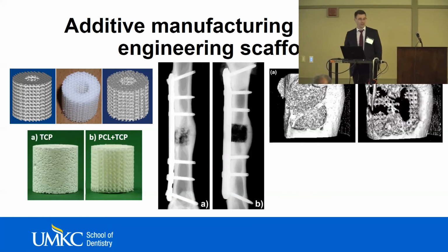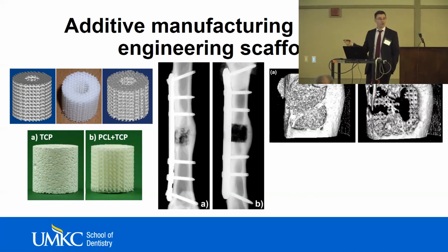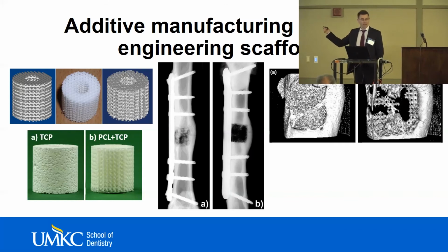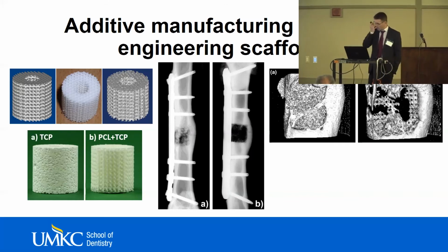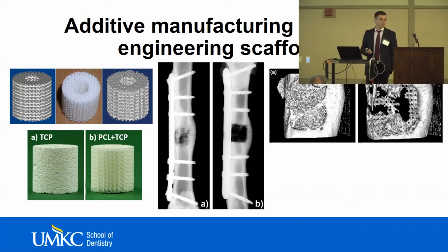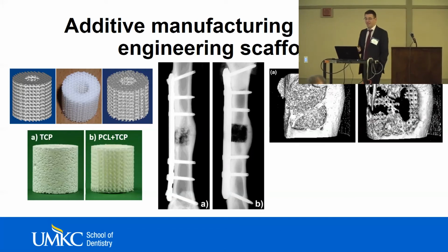The micro CT scan then actually told us that we do have some bone ingrowth on the right-hand side in our polymer scaffold as well. So this looks like scaffold material, but actually it's the bone that left gaps where still polymer is in place. Nevertheless, the TCP scaffold was better. I have to admit that. The PCL material is probably not the best for this type of bone formation.